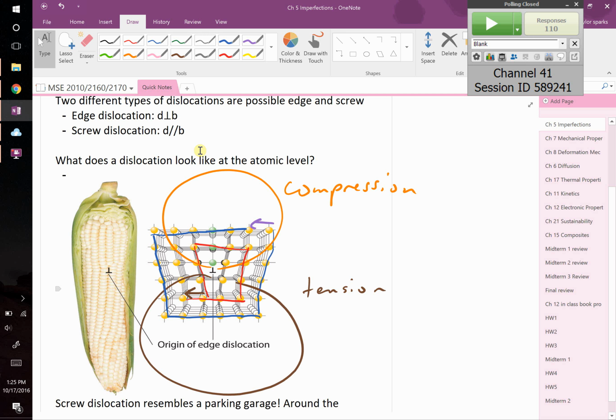They're both causing stress in the lattice, which they don't like. So if you've got an impurity that's too small, and you've got a dislocation that has a region where it's too crowded, they go together nicely. If you have something that's too big, let's say you're sticking a big atom inside of there compared to the host atom, it's going to want to go right here, somewhere where it's already being pulled apart, so just put a big atom there. So dislocations and impurities become really important. It's hard to separate the two because you have to go up in energy in both regards when they separate. It's lower in energy when they come together and they stay put.